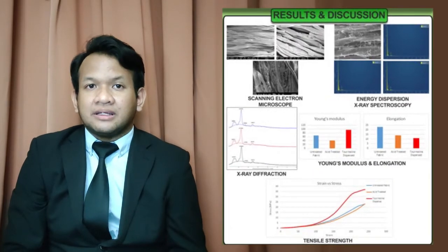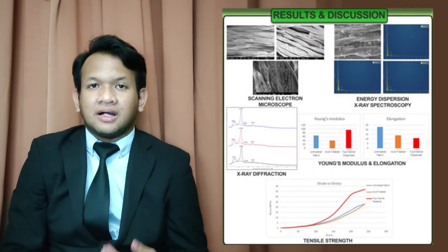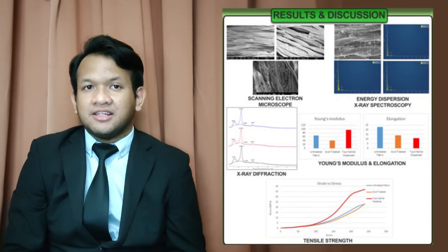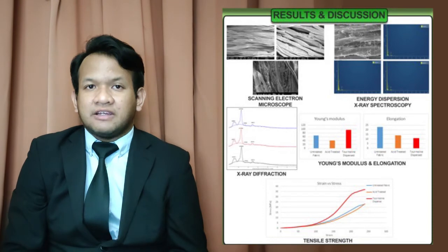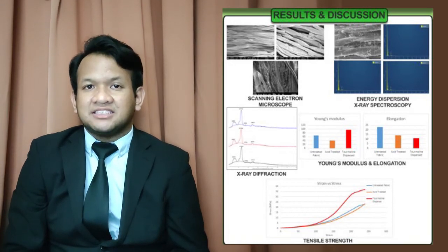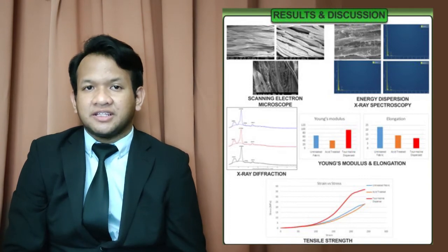The figure shows the SEM image of untreated, acid-treated, and tourmaline-treated fabric. From the figure, it can be seen that the untreated fabric has a smooth surface due to the structure not yet being modified. As the fabric is treated with acid, a small morphological change of the surface can be seen as the surface becomes rougher due to the opening of free space on the treated surface. Acid treatment helps make the cross-linking reaction of tourmaline to the fabric easier.